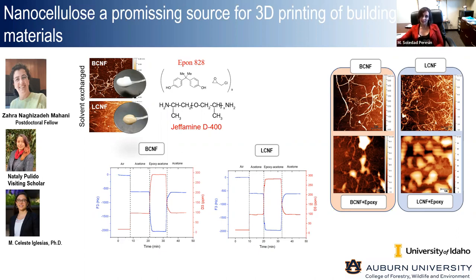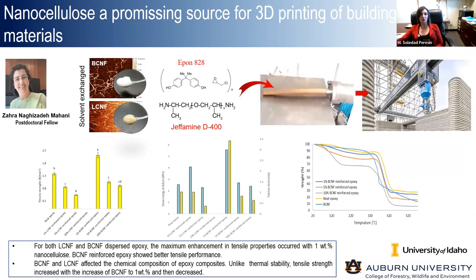So very early stages, again, we are working on this, but what we have managed to do is identify the loadings of nanocellulose in terms of the epoxy resin. In this case, up to 1% of nanocellulose content in the epoxy will improve the mechanical properties and as well the thermal behavior.